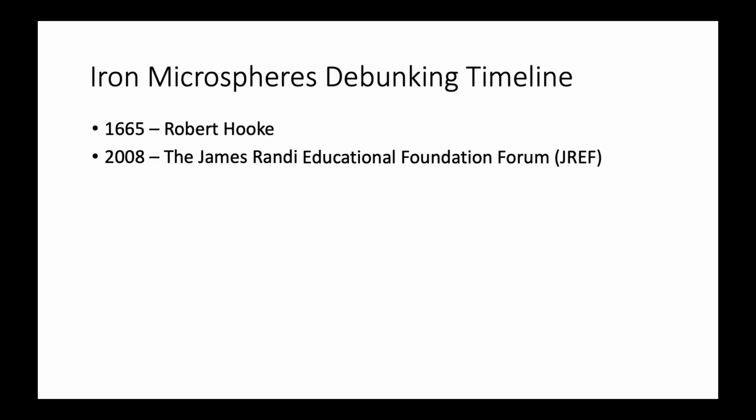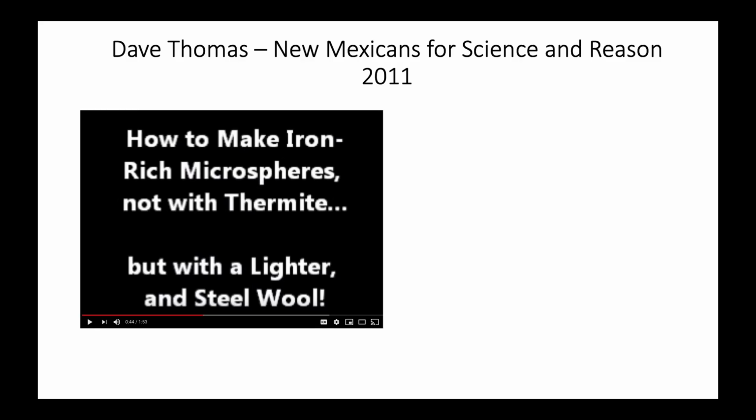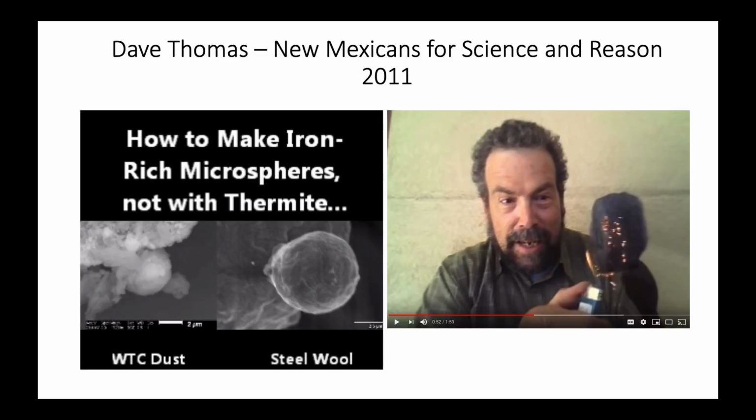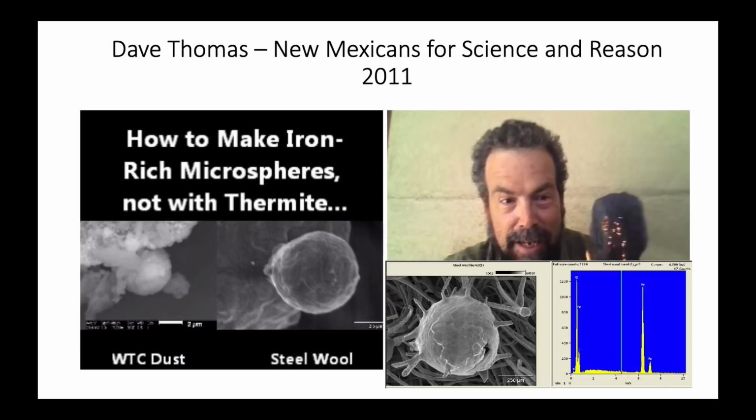So next on our timeline, we have 2011 and Dave Thomas. Dave Thomas, in 2011, made this video, how to make iron-rich microspheres, not with thermite, but with a lighter and steel wool. He did a very simple experiment, similar to Hooke's experiment with the iron filings, where he took steel wool, lit it with a lighter and burnt it, and it created some iron microspheres. He took photographs of them, he did some analysis of them, and he found that they were pretty much the same as the iron microspheres found in the World Trade Center dust that people had been analyzing.